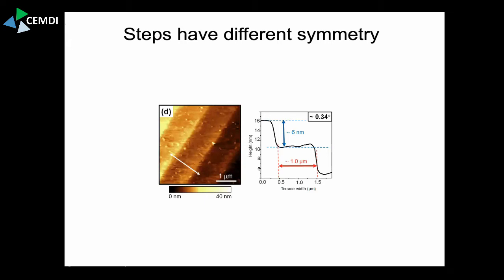If you take a very careful look at this picture, this is not a staircase that you would like to walk on. If you see a picture like this from a staircase, you see, oh, you're probably going to trip here. This is a little bit higher than necessary. So that means your step is slightly higher here. This is not a coincidence. This is due to the fact that the diffusion of surface atoms at the edge is slightly different, ever so slightly. It's known as the Ehrlich-Schwoebel barrier, and it comes from a broken symmetry of your system.